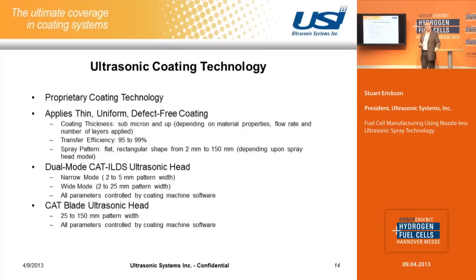So the capabilities of this technology, when integrated into the proper coating system design, you can apply very, very thin coatings down to sub-micron dry coating layers with a very high transfer efficiency. And the rectangular flat pattern from anywhere from 2 millimeters wide up to 150 millimeters wide, depending upon the spray head that we're using. We have two basic model spray heads. The blade head is what we showed initially in the description. It can produce a pattern from about 25 millimeters up to about 150 millimeters.